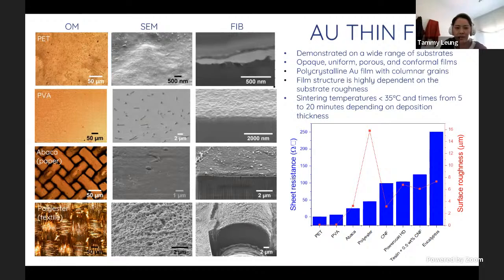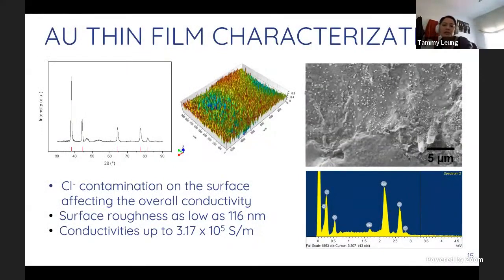Something else to note is that the gold film that was deposited onto PET showed columnar grains, symbolizing the polycrystallinity of the film. And this was verified using XRD, which showed excellent matching diffraction peaks across the surface, where any additional peaks were contributed by the PET substrate below. Additional analysis was done using SEM and EDX, which showed some chlorine contamination on the surface, which is seen as salt crystals.